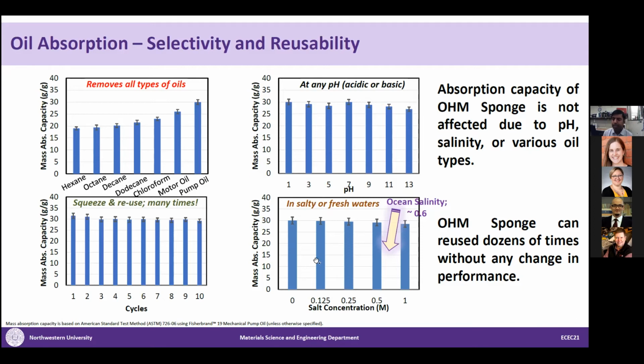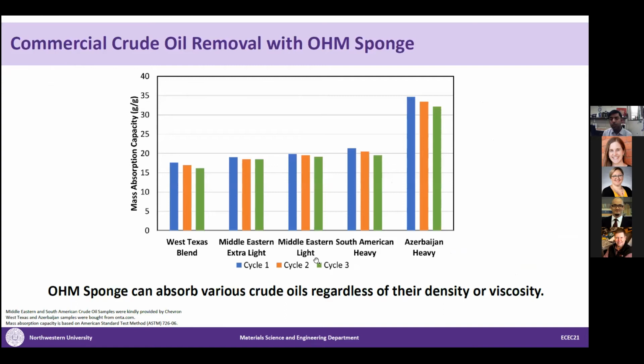After this, we tested crude oil. We acquired some crude oil from our collaborators at Chevron, and we tested 5 crude oils that differ in viscosity as well as density. And what we see here is it works on all sorts of crude oil, whether it's West Texas, which is very less viscous, to Azerbaijan heavy, which is a highly viscous oil. It works on all oil. The capacity changes because of the change in the viscosity of the oil.